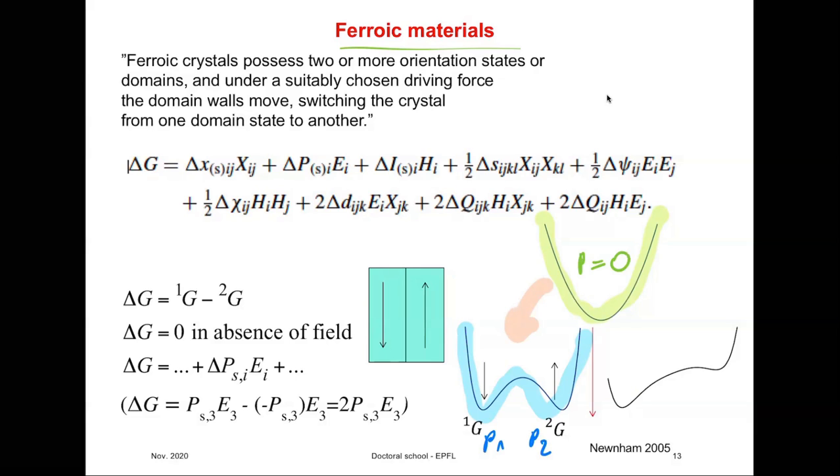And then when we apply an external electric field, we are introducing an asymmetry between these normally equivalent states. They are no longer equivalent. One of them is preferred with respect to the other. Okay, so this state is preferred to this one. It has a lower energy, and the difference in the energy between these two states is a driving force for